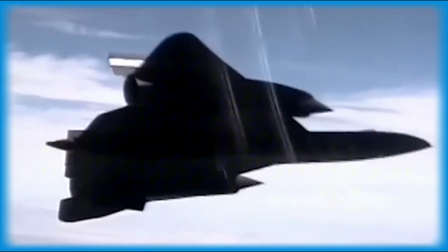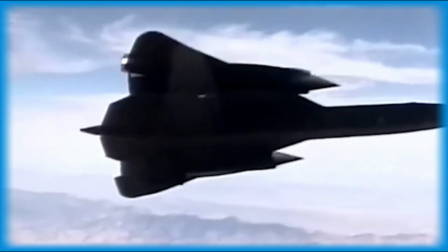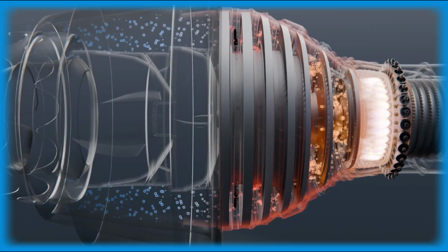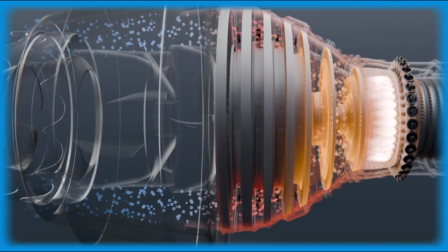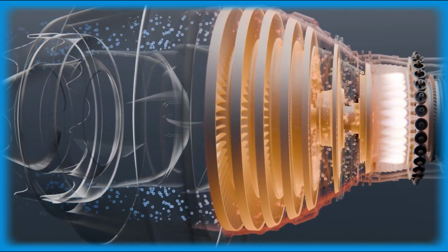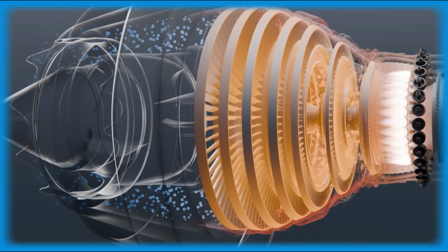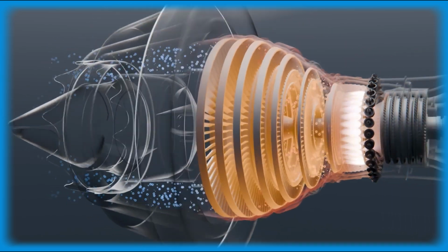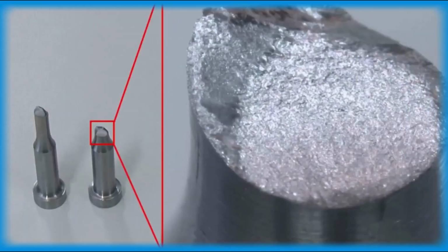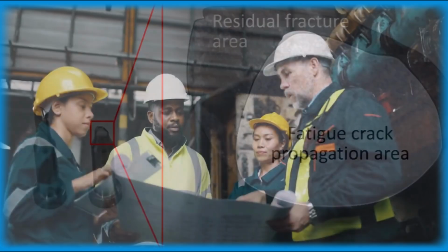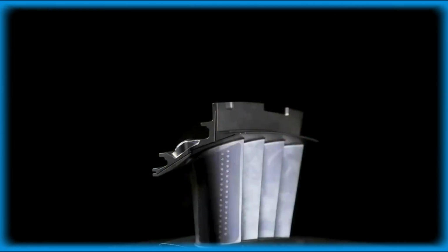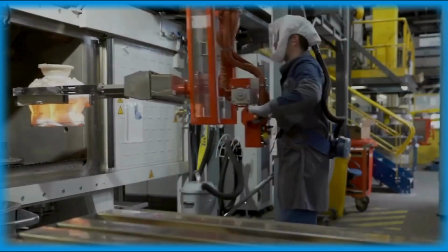However, neodymium magnets have a significant operational vulnerability: they lose magnetic strength as temperature rises. This phenomenon, known as coercivity reduction, is a serious concern in aircraft, where temperatures can range from -60 degrees Celsius at altitude to well above 150 degrees Celsius near engine nacelles and avionics bays. Dysprosium, element 66, addresses this directly. When added to neodymium magnets in concentrations of 2 to 6%, dysprosium significantly raises the coercivity of the magnet, maintaining field strength across the wide temperature range experienced in service.